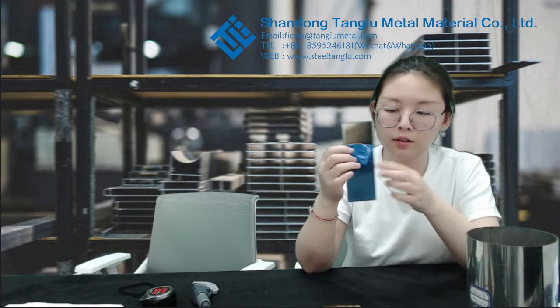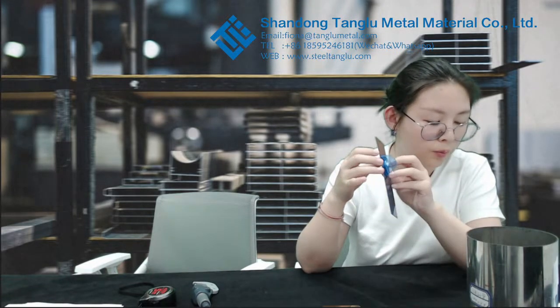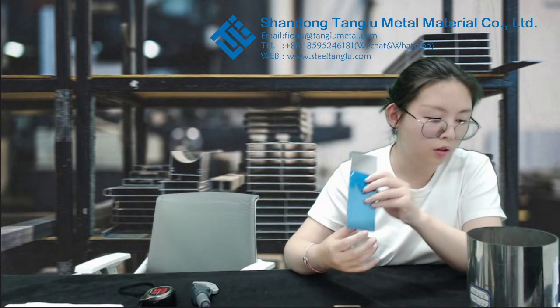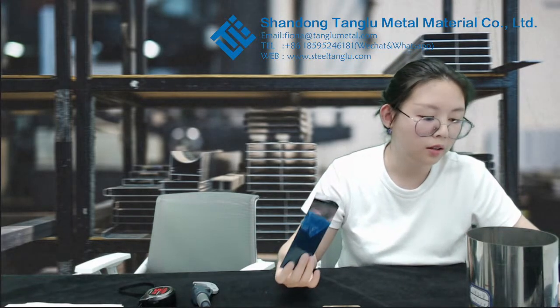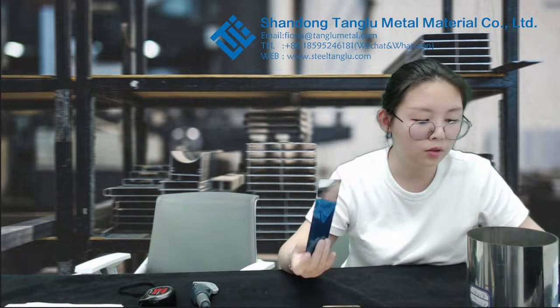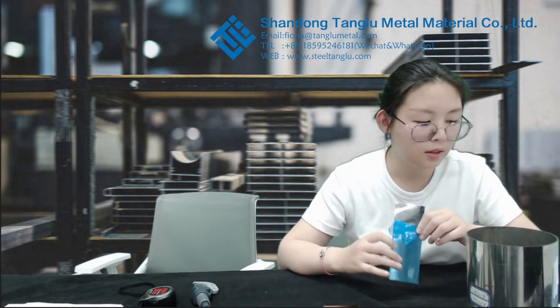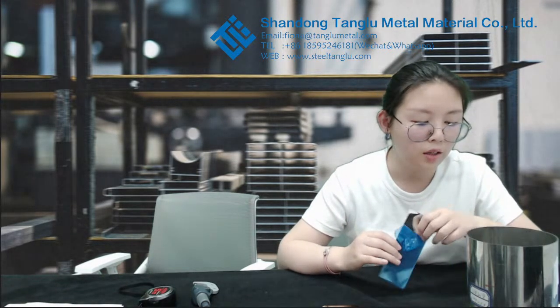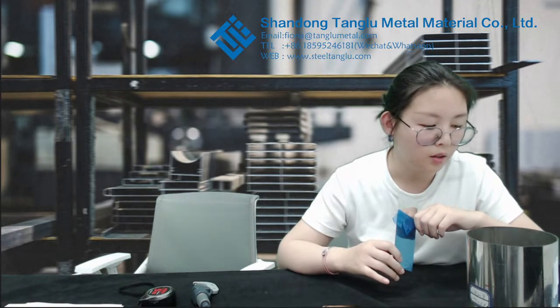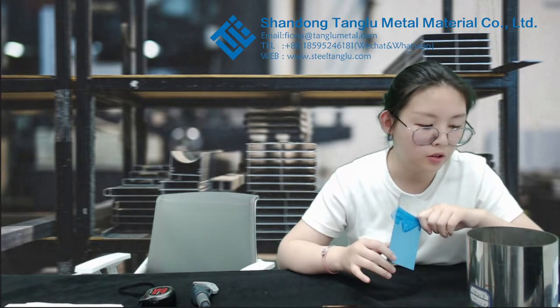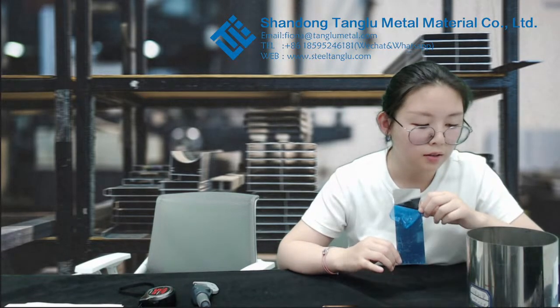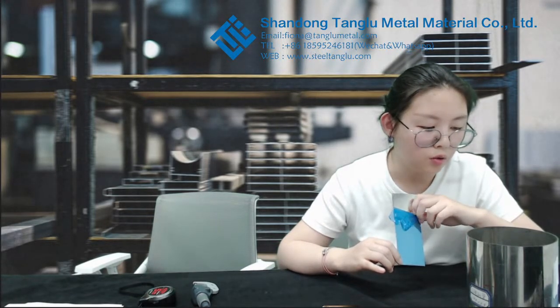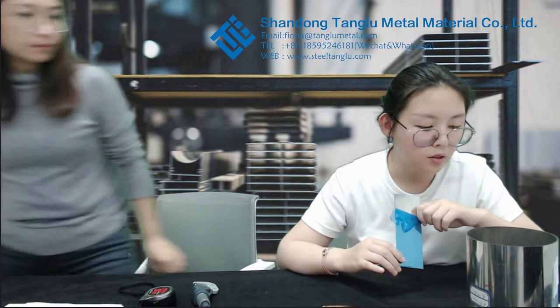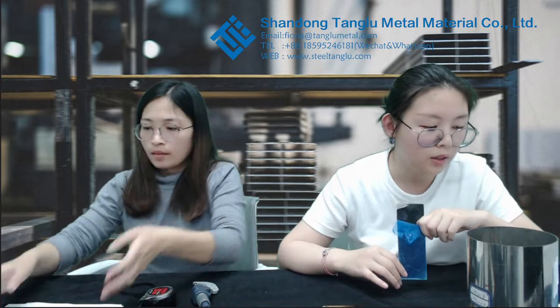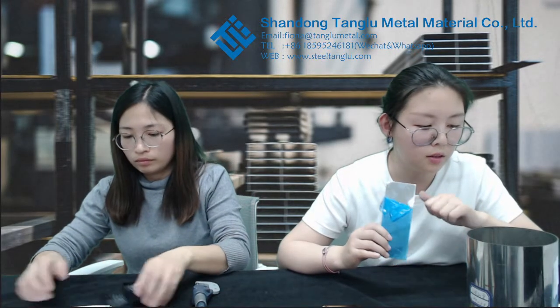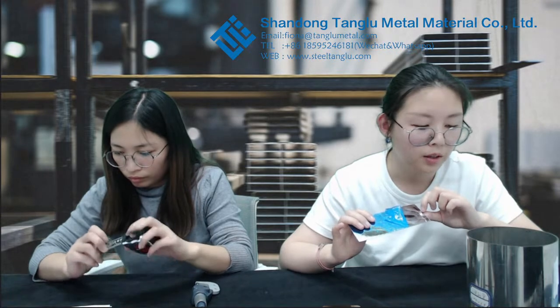So this bright surface is mainly for cold rolled steel. Let me introduce the cold rolling process. Generally, the raw material of cold rolling is hot rolled stainless steel coil. The hot rolled coil should first be decoiled, pickled, and descaled in preparation for the following procedures. Then it is fed to cold rolling mills. In this step, the stainless steel sheet passes through a series of rolling mill stands which squeeze the sheet to reduce its thickness in the cold state.